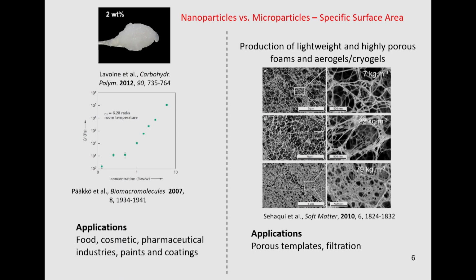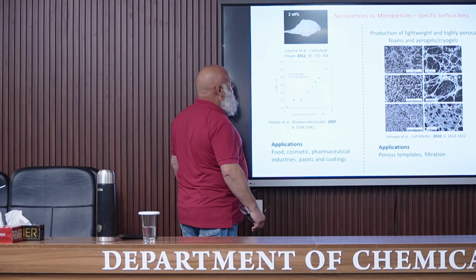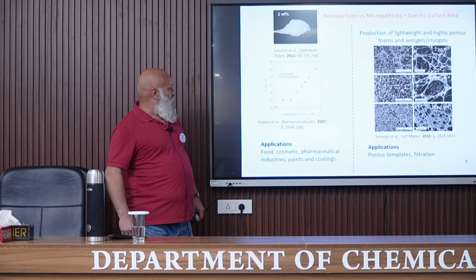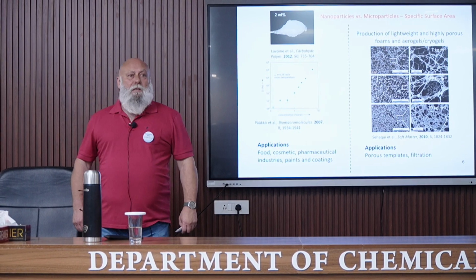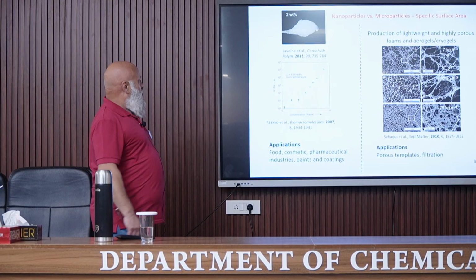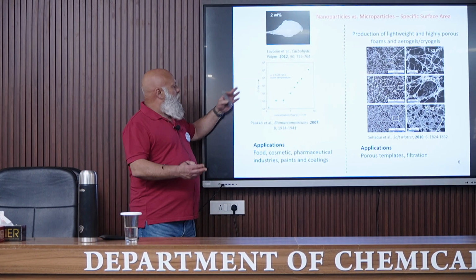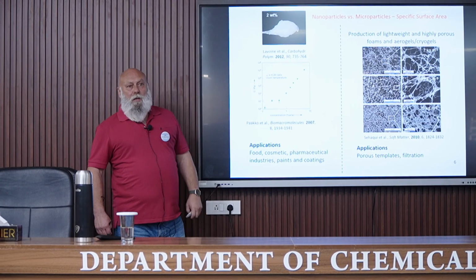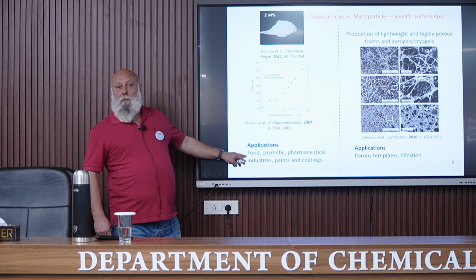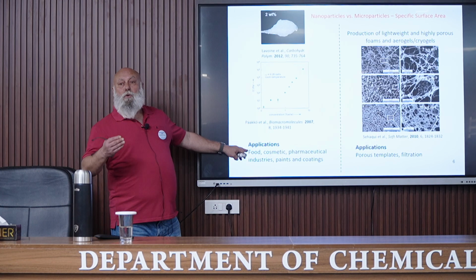A first consequence of this is that when these nanoparticles are in suspension in water, of course, a lot of water molecules can interact with the surface. They interact, and of course, the mobility of these water molecules is reduced. And the consequence is this: we obtain a gel for a very dilute suspension, here 2% of eucalyptus nanofibers in water. Another consequence, we have seen also this figure previously, is the increase in the viscosity of the suspension, because the water molecules are immobilized at the surface of the nanoparticles. So this is the storage modulus and the viscosity as a function of the concentration, and we have this huge increase. Resulting applications: food, of course, the suspension can be used to control the viscosity of food.